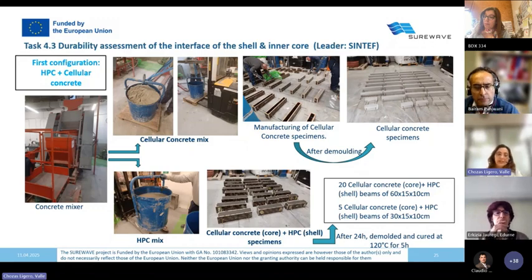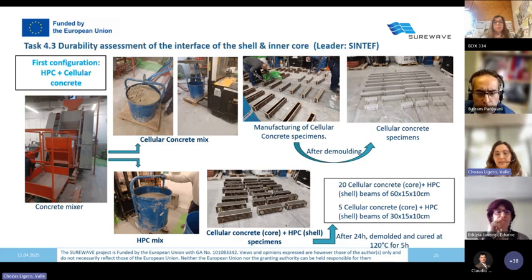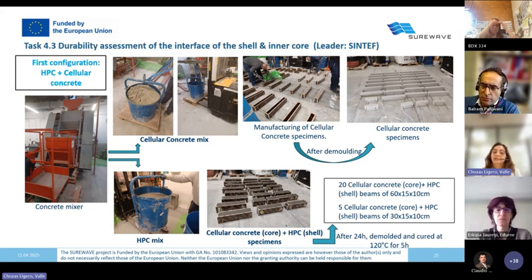Regarding this work, I'm only going to talk about the manufacturing of the specimens and the measurement of the interface of the shell and inner core carried out by SINTEF. The process for manufacturing this specimen was to first make the cellular concrete, and then make the high performance concrete for the shell. After 24 hours, the specimens were demolded and cured at 120 degrees for 5 hours.